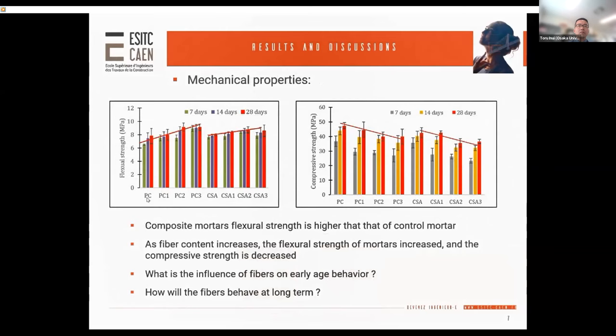As a result, we are presenting here the mechanical properties of the mortars at different ages, from 7 to 28 days. As you can see, as fiber content increases, the flexural strength of mortars increased significantly, causing a decrease in compressive strength. 2% of coconut fiber content seems to be an optimum for improving the flexural strength of mortar.